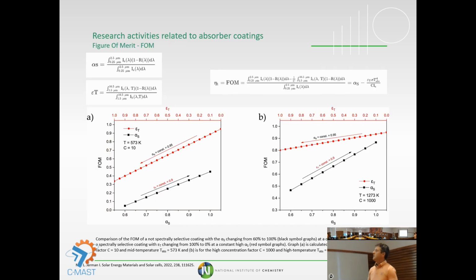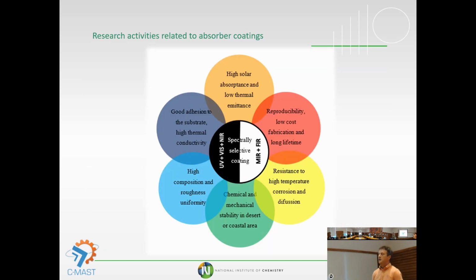In order that it works in the industry, we normally do some calculation of a figure of merit, to see how our coatings should work, and how important it is at low temperature, with low concentration maybe, or with high concentration, how those values influence the coating. As you can see, it is much more important in the case of selectivity when you are dealing with high concentration in contrast to low concentration. So our activities to optimize the coating were in the past really on all aspects.